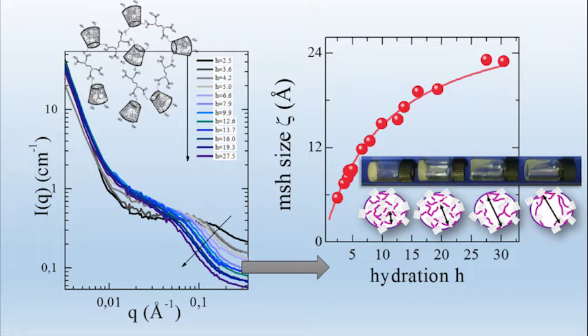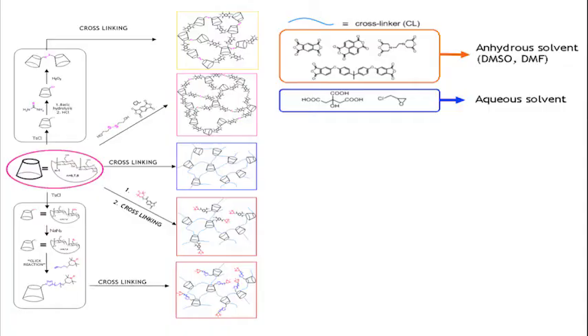How can ibuprofen enter the nanosponge? Yes, to achieve the entrapment of ibuprofen, we exploited the properties of one of these class of material, the cyclodextrin nanosponges. So it's the capability of absorbing water with a phenomenon which is known as swelling. Strictly speaking, we start with the dry polymer, which is basically a white powder, and we contact this powder with a solution containing ibuprofen. After a while, the polymer is able to absorb water, and it turns from a white powder into a transparent, highly viscous, and homogeneous hydrogel.